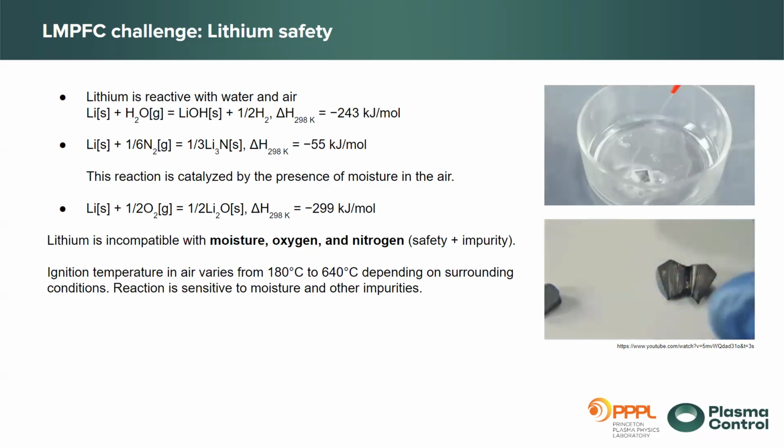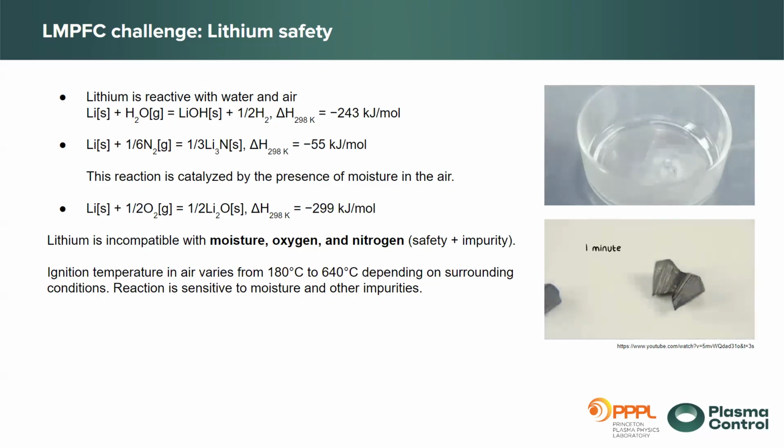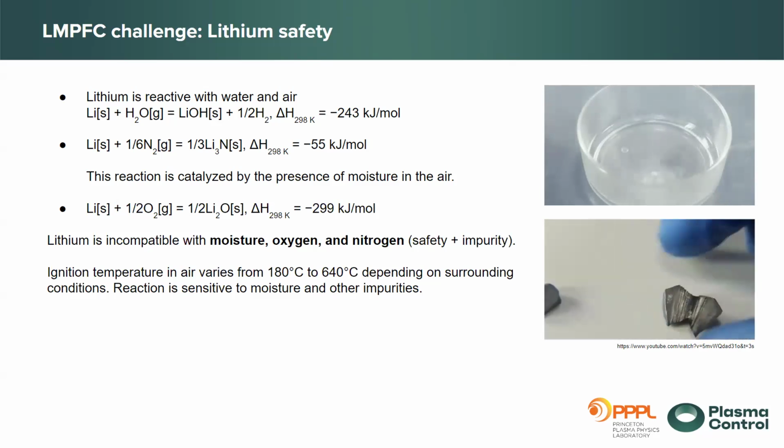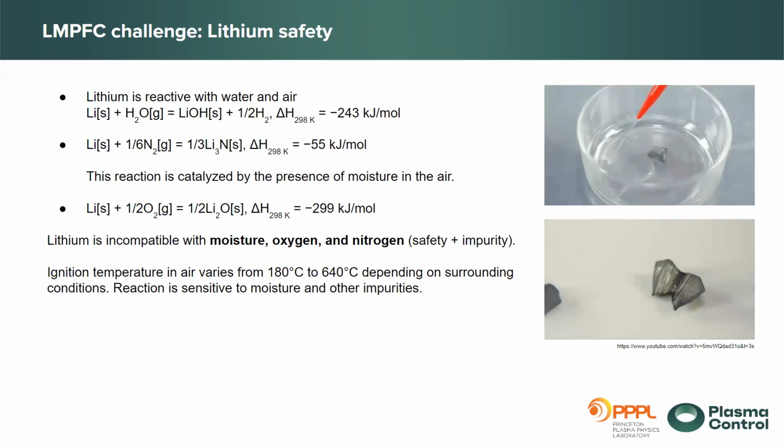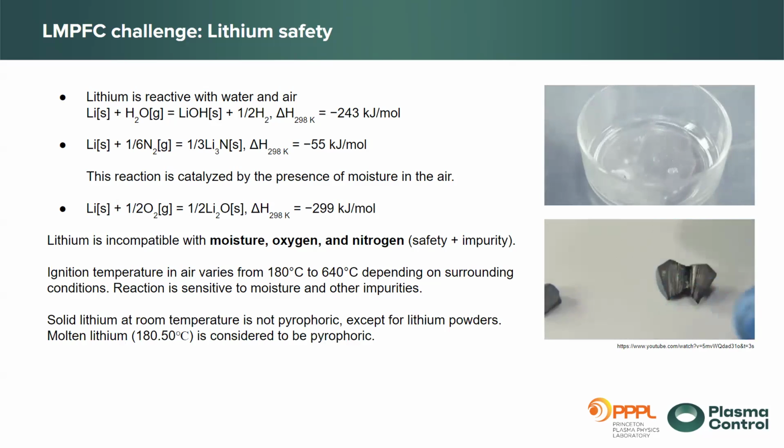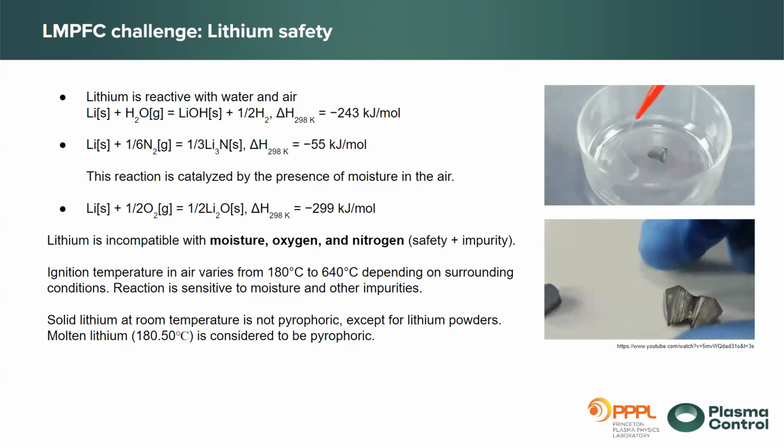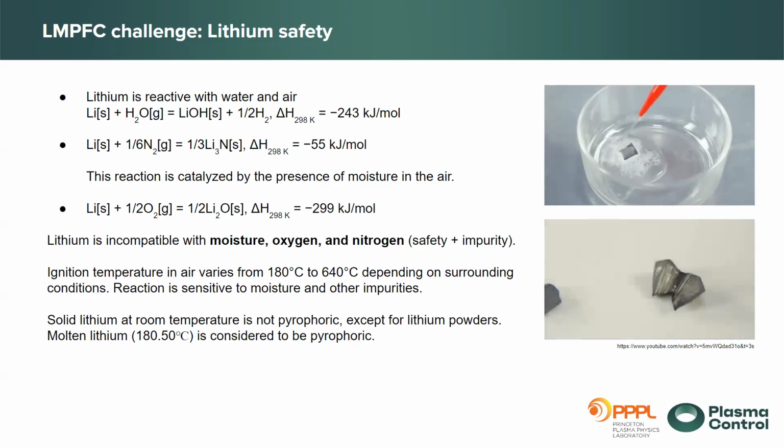Also, the ignition temperature in air for lithium varies from 180 degrees C to 640, depending on surrounding conditions. And the reaction, of course, is again sensitive to moisture and other impurities. Solid lithium, however, at room temperature is not considered pyrophoric, which means it's not going to burn on its own.